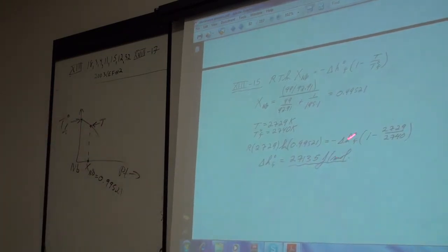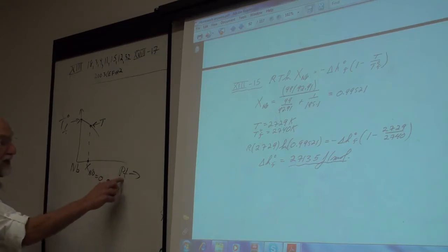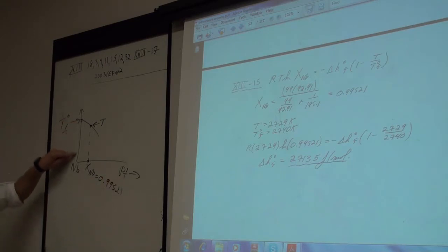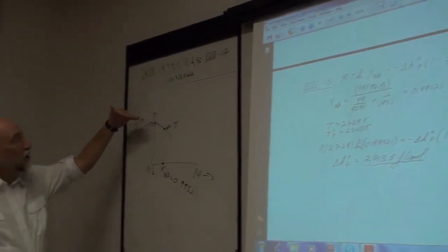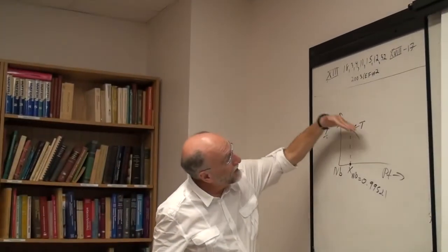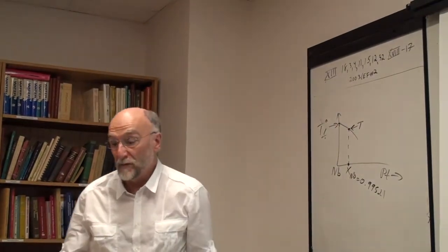Okay, and so we end up then from this getting the heat of fusion. And of course, this would be the same as you pointed out last week. It doesn't matter that it's platinum; you can put any other metal here, as long as it was insoluble in the solid niobium, you would get the same liquidus point in the limit as X niobium approaches 1. If it, of course, gets more concentrated, then the various liquidus lines are going to be different.